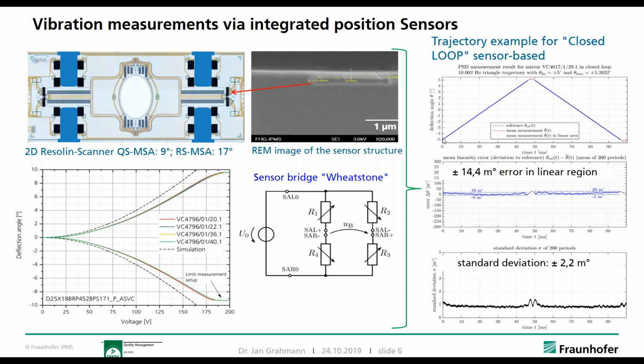We tried, by a closed loop regime, to drive the scanner as linear as possible within that range, or for different trajectories. Now you have to know that, as you can see here for that quasi-static axis, you see a drive voltage and a deflection angle. And the correlation between deflection angle and drive voltage already is not linear. So we compensate for non-linearity by a certain drive scheme, and then the correction by closed loop control in order to keep the scanner linear.